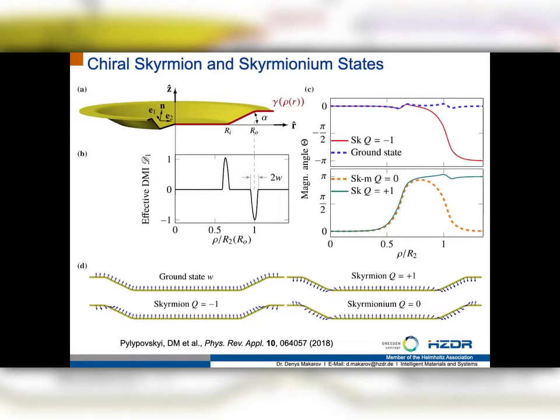And in this case you will have different states which are the ground state, for example, homogeneously magnetized, or the one which will have only one domain wall, which will be a Skyrmion state, or with two domain walls where you will have Skyrmionium states with different topological numbers. And what is important, these domain walls are also chiral because of the curvature-induced Dzyaloshinskii-Moriya interaction.